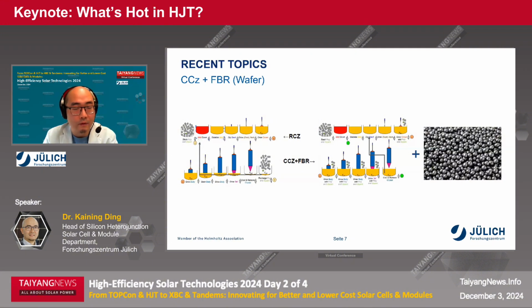But as I said, heterojunction wafers do not require the same quality as the TOPCon due to the low temperature processing. So all in all, if you combine this continuous CZ and FBR granulate, this is a very strong tendency towards cost reduction on the wafer side, in combination with the thinner wafer trend. So I think there is a lot of potential for lower cost for heterojunction in terms of silicon cost.